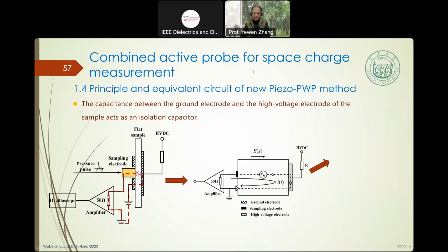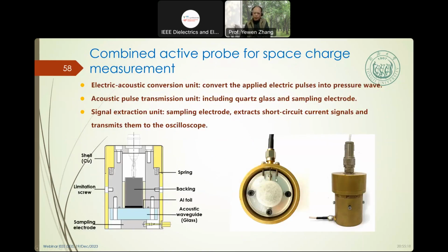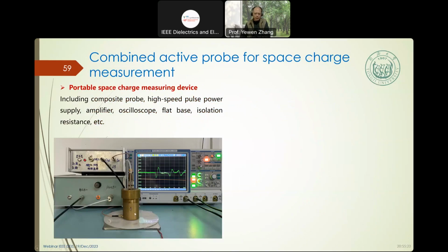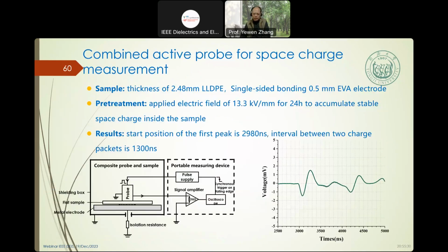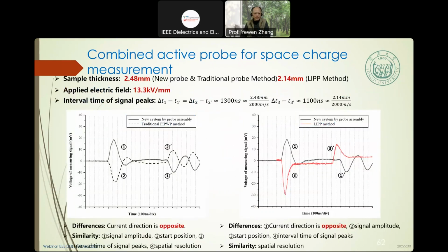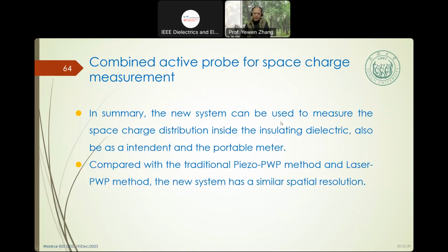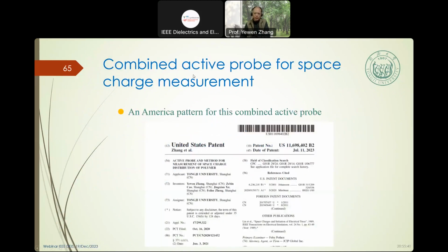So we give quickly the new result for the combination. We combine the sample. So we developed the active probe for measuring the space charge by the piezo and using the compensation. This one is a probe. This is a probe for the space charge measurement. So the result is very similar to the laser. The combination is similar. The new system can be used for measuring space charge distribution inside. Also, by combining with the traditional piezo, PWP or laser, the new system has very similar spatial resolution.